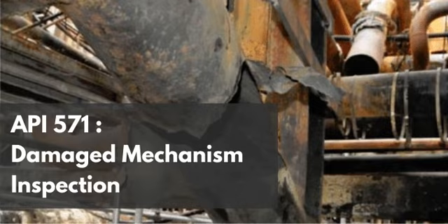Oh, it's a bump on our flat riverbed. Exactly. It is the boulder in the river. You have the hottest fluid in the unit, heavily degraded into corrosive acids moving at high velocity. It hits that slight weld protrusion, and it creates massive localized turbulence. So it's that mechanical stripping again? Yes. The fluid churns, strips away any protective scale, and carves that canyon directly into the weld root. It is mechanical fluid dynamics accelerating chemical dissolution at a microstructural level.